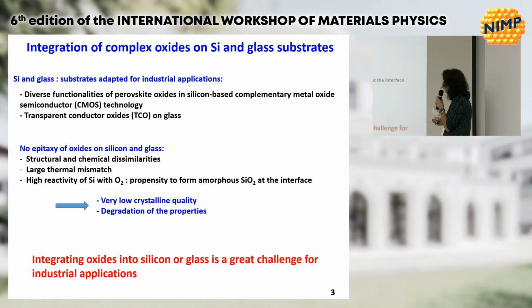But of course, there is no epitaxy of oxide on silicon and glass because of structural and also chemical differences. There is also a problem with the large thermal mismatch between substrate and thin films. And at the end, the silicon also reacts very strongly with oxygen to form amorphous silica on the top. So the films we grow on it present very low crystalline quality, and of course you have a degradation of properties in this case. So integrating oxides on silicon and glass is still a great challenge for industrial application.